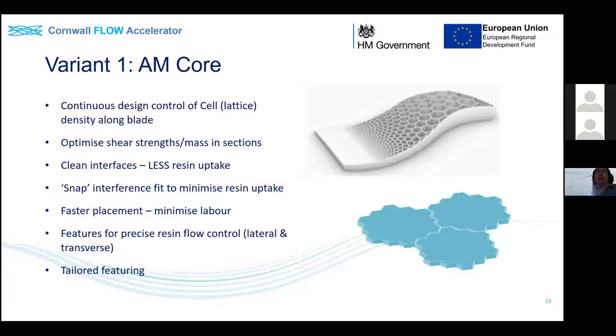So we'd look to also make that fit quite highly toleranced, so there'd be a snap interference to minimize the amount of resin which is taken up even at the joints. But it also allows opportunity to locally control the flow of resin infusion and minimize the time of resin infusion over current resin infusion techniques, because you've got a very fine amount of lateral and transverse flow according to where you put through channels, which can be closed.